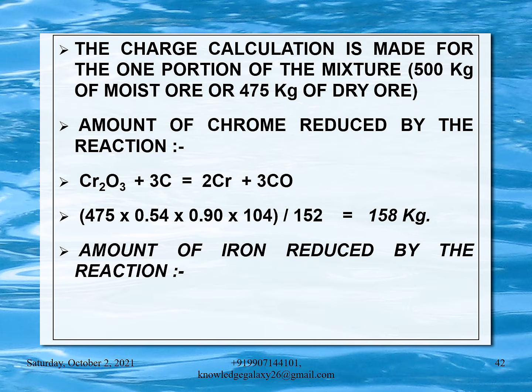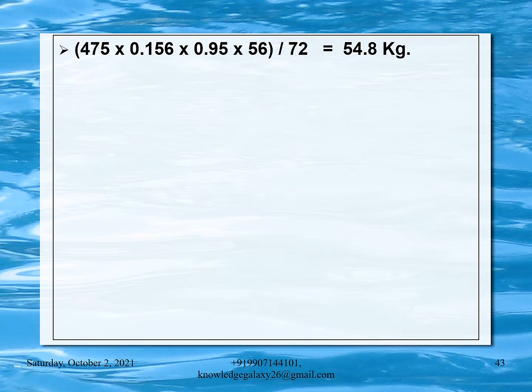Amount of iron reduced by the reaction FeO plus C is equal to Fe plus CO. It comes to 475 into 0.156 into 0.95 into 56 divided by 72 is equal to 54.8 kg. Here 0.156 is the 15.6% of FeO content in the ore, 0.95 is the reduction of FeO from the ore, and 56 is the atomic weight of iron, and 72 is the atomic weight of FeO.